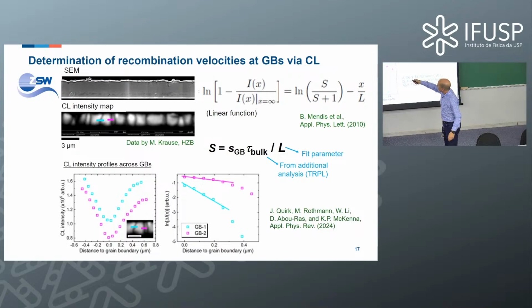What we do is this: this is a cross-sectional SEM image of a thin film solar cell. You have the back contact here, the front contact here, and this is the absorber, right? And the absorber is polycrystalline, and you can see this quite nicely because in the cathodoluminescence intensity distribution, you see decreases wherever you have grain boundaries. What I don't show here is that at the same position, we acquired EBSD maps that confirm indeed that we have grain boundaries exactly at these positions. Okay. Then what we do is to extract profiles across grain boundaries. They look like this, okay? And we can confirm by EBSD that the position of the grain boundary is about where the local minimum is. Okay, this is as expected.